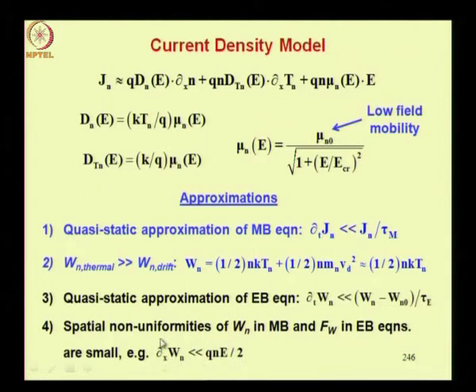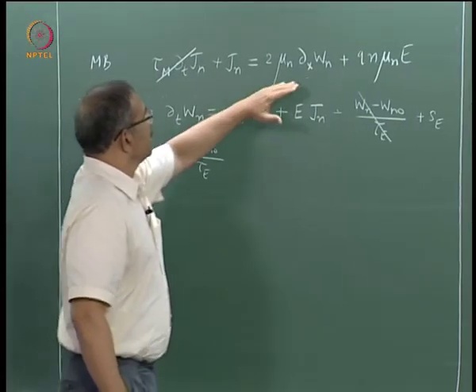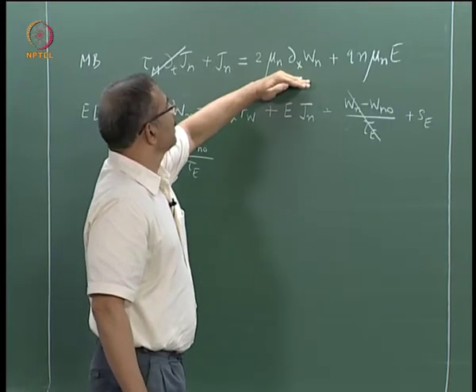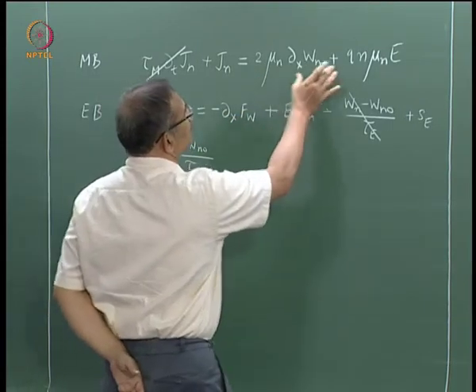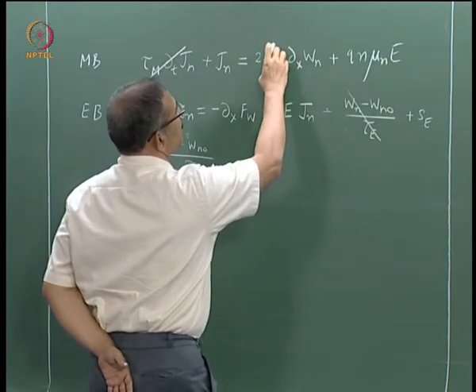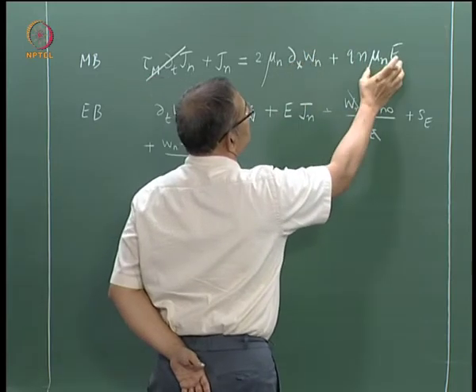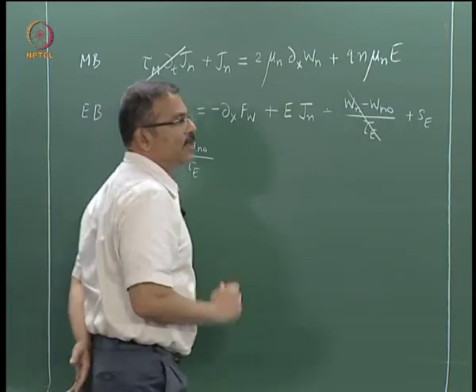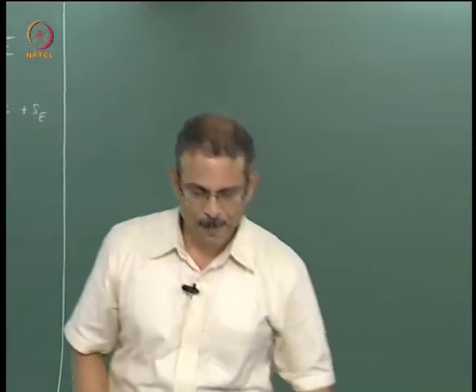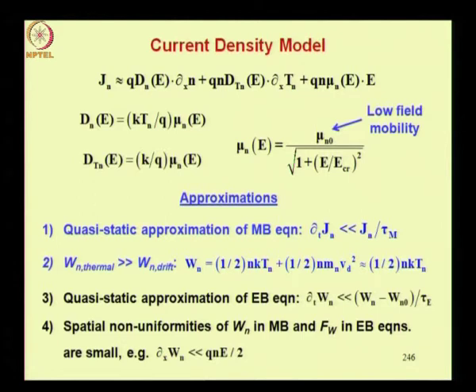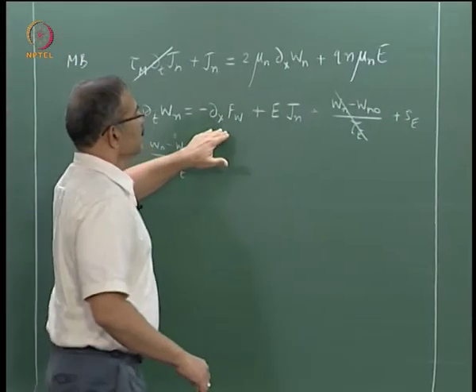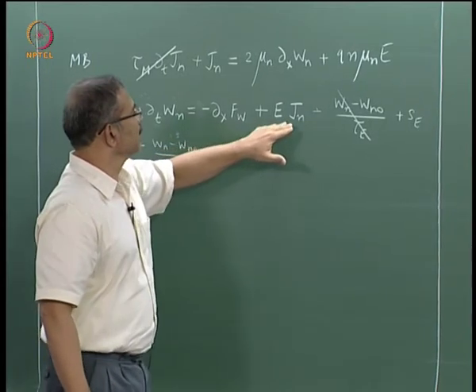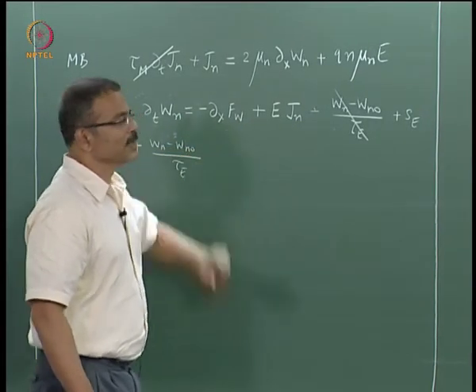So here again we are comparing the term that we are neglecting with other terms in the equation. Look at this. So dou Wn by dou x in the momentum balance equations comes here. Now we compare it with this term. You can see that mobility can be removed, and so if this term is much less than this term, then you can neglect this term. That is what we are saying. One can similarly write down an expression for neglecting Fw. If you want to do that, you should look at the terms here. You can compare it, for example, with this term for neglecting, and you can write down a similar relation.